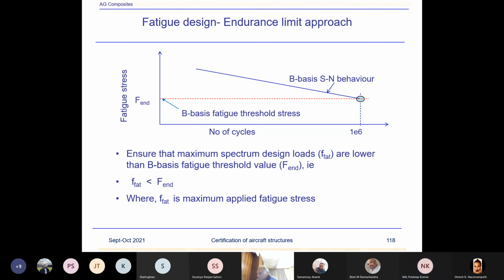Yes. Now, what happens is the way the curves are generated. There are some correction factors which, say, Boeing would have generated if we are testing a coupon using constant fatigue loading, constant amplitude. But then, in order to generate this 95/B basis curve, we apply the correction factors for the spectrum loading, and also the component factor. So you are testing coupons, but a large component may behave differently. Generally the company has factors based on a lot of test data historically. So they specify this much of a correction factor in order to bring down the curve from the coupon level so as to behave like a component.